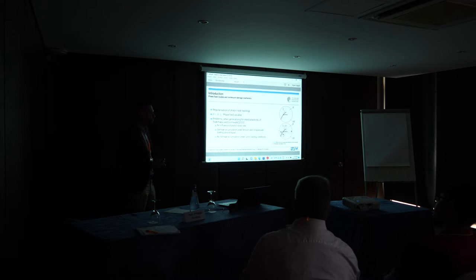If we want to extend this approach to describe ductile fracture, and if we try to do this by simply combining a brittle phase field model with an elastic-plastic material law, then it is most likely that we will get unphysical results due to completely different fracture mechanisms. For brittle fracture we have debonding of atomic planes, whereas for ductile fracture we have initiation, growth, and coalescence of voids due to evolution of plastic strains. The biggest problem is that in an elastic phase field model there will be no influence of the plastic strain rate in the damage evolution.